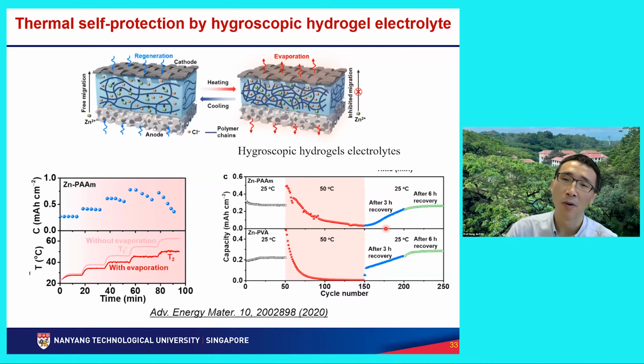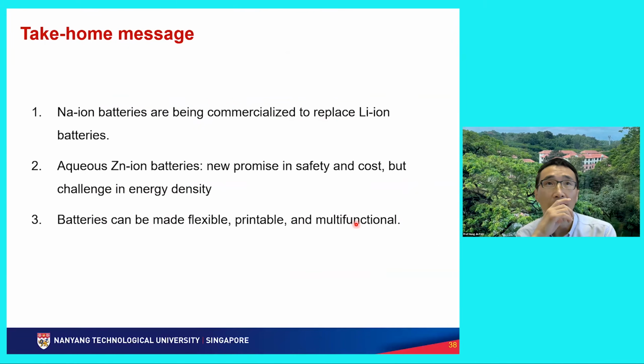Yes, the response is quite slow, and it's because the polymer gel is not optimized yet. If someone can optimize the polymer gel or optimize the porous, foam-like structures, the water can evaporate and reabsorb faster. Then the response could be much faster. Okay, so we used two kinds of materials, PAM and PVA, to test the response. They have a similar response, but again, the response time is too slow. Okay, I think it's about 1 hour.